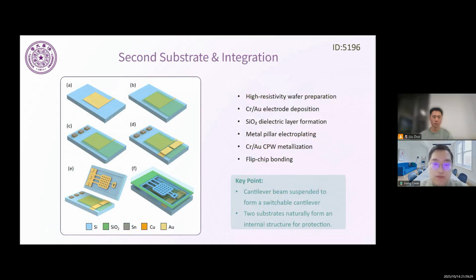On the second substrate, we build the RF environment. We start with a high resistivity silicon wafer, and here's what we do. First, metal sputtering to form the base layers. Second, dielectric deposition for insulation. And third, copper pillar electroplating. These will align with the ones on the SOI side. Then coplanar waveguide metallization. This is where the RF signal travels. And finally, flip-chip bonding to join the two substrates together.